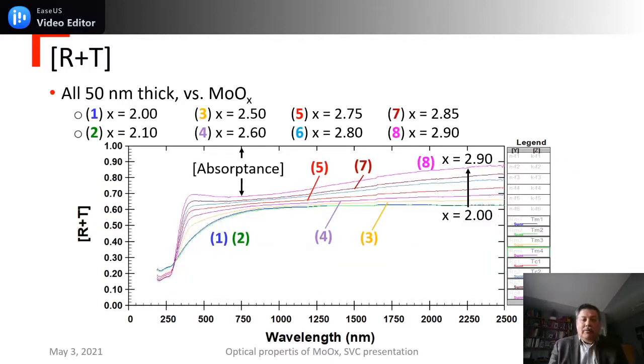Now, one of the things that one should be in the habit of is to look at the sum signal of R plus T, because this eliminates all effects of interference fringes. If you do it right and the sample is uniform enough, you should see no hint of residual interference fringes. And the point is that the absorptance can be seen as the difference between 1.0 and the actual signal here. I find this very instructive to get in the habit of looking at.